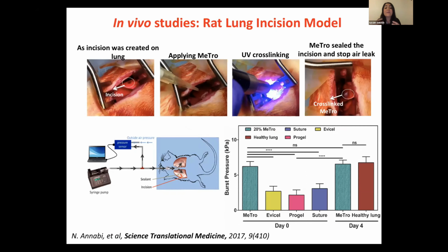Tropoelastin has this thermoresponsive property. Once it touches the surface of the tissue at 37 degrees, the polymer aggregates. And as we have this aggregation, or we call it coacervation, it is confined to the defect site on the lung. And then to further stabilize it, we use light to photopolymerize it on the tissue. And after exposing to light for less than a minute, we could form a very nice seal on the defect.